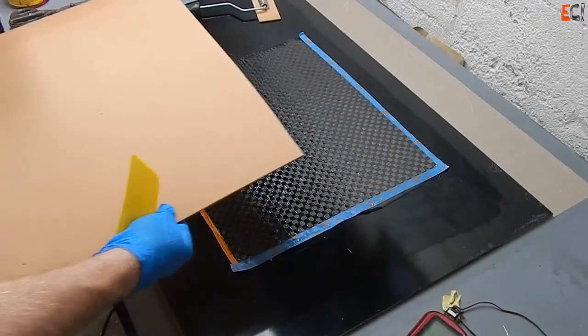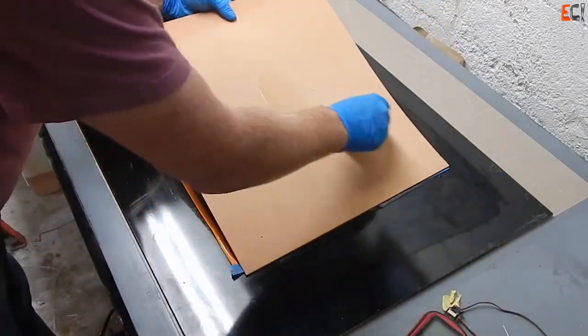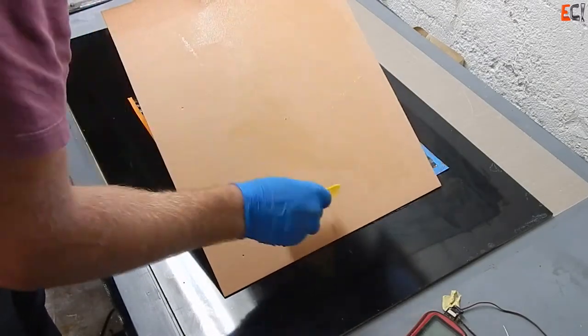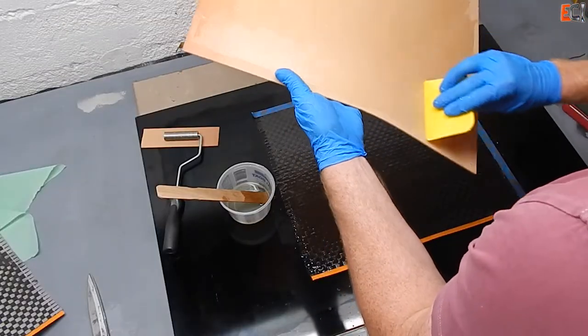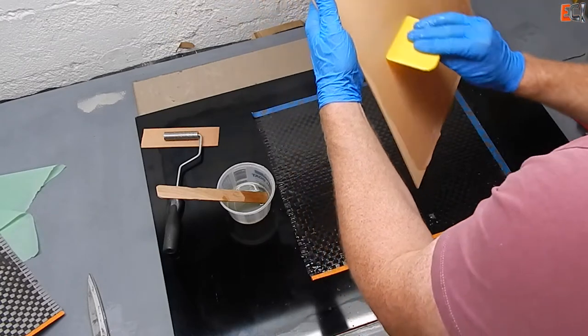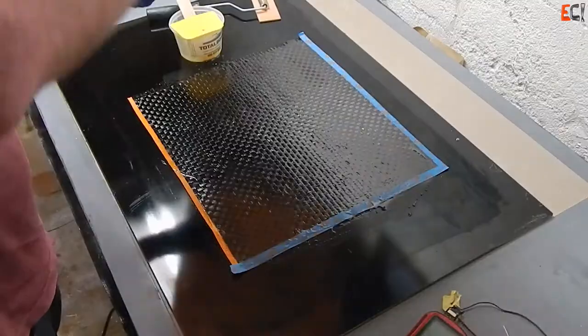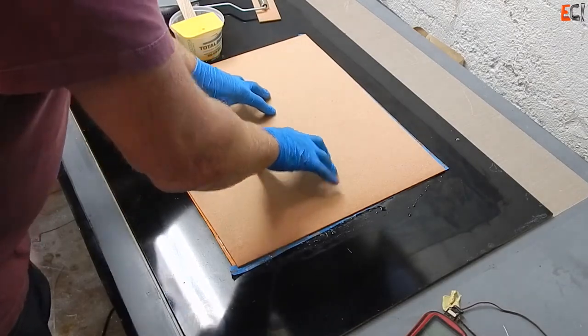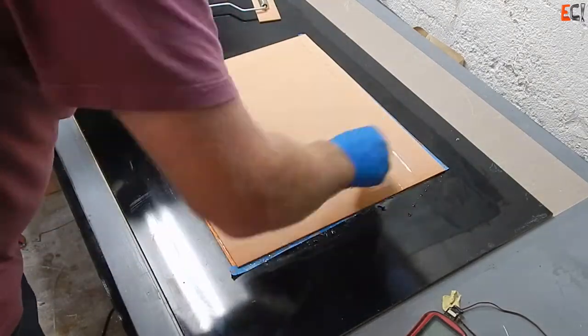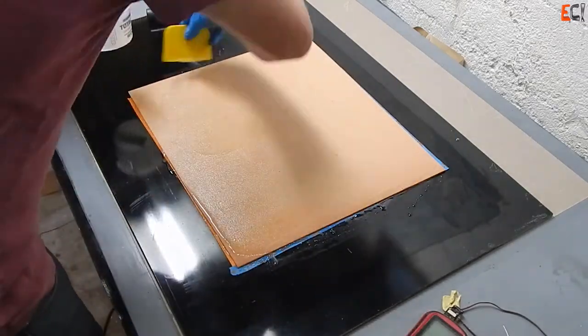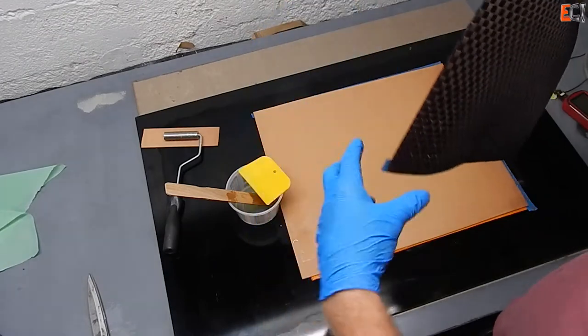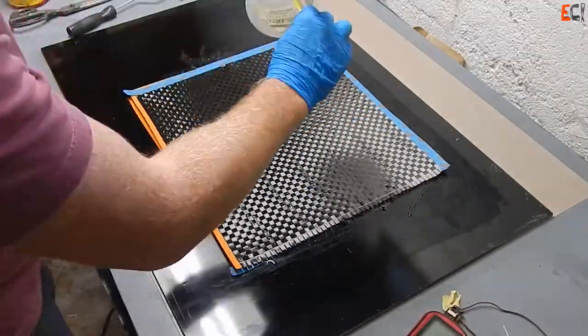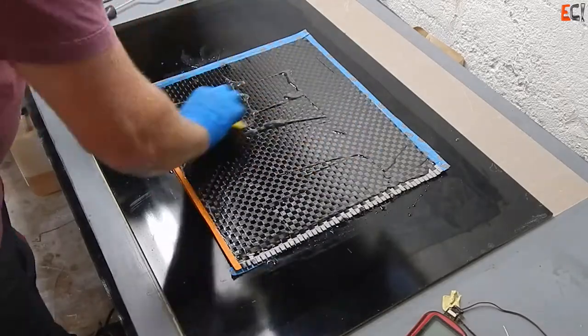So here goes the core with no holes in it. And all that resin at the bottom isn't going to have anywhere to go. I wasn't sure how bad this would be, pretty good idea there would be air in it but that's part of what we're showing here. Wetting out the core on the bottom so there's resin on it, ideally that would be with some filled resin for something with heavier skins or thicker core but here it would be fine just using straight resin like this and now I'm wetting out the top and putting down this top skin. This is really nice stuff and it wets out beautifully and doesn't use an awful lot of resin and it looks really neat.